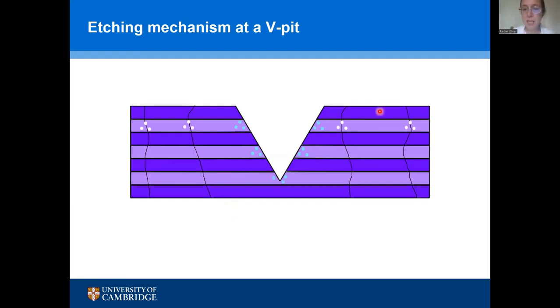To start with, we have etching happening down the dislocation core, but also via the V pit. But the etching can access far down into the structure from the V pit because it's just straight there. It hasn't got to form a pipeline or anything. It can just dig right in. So as we continue to etch, the etching via the dislocations may be happening quite slowly, but there's this short circuit route from the etchants to the lower layers. So layers further down are really dominated by the etching via the V pit, which means that by the time we get into the deepest layers of the structure, our entire morphology is going to be dominated by etching from this large feature that's not really intended to be in our sample.